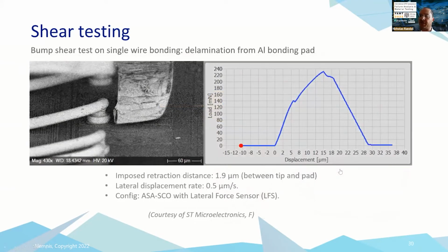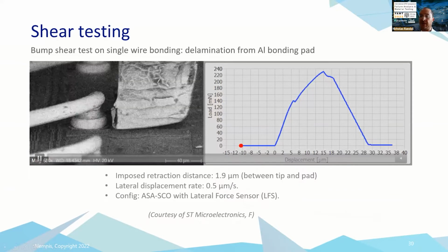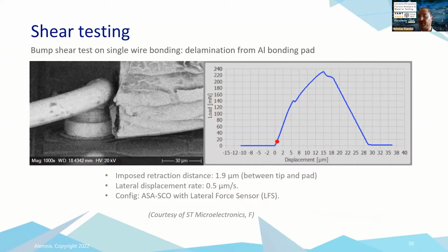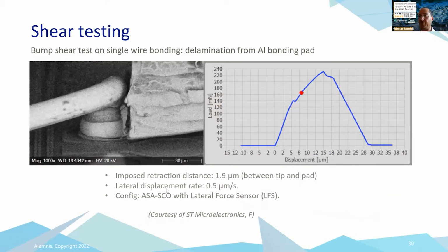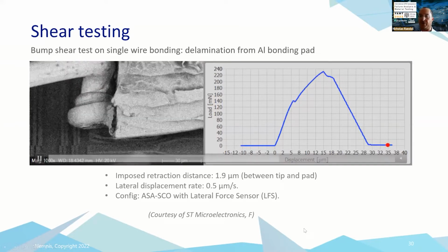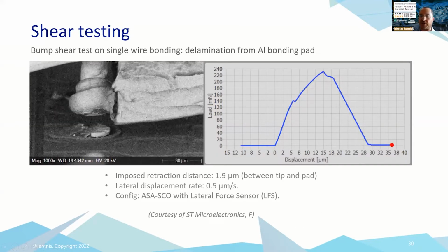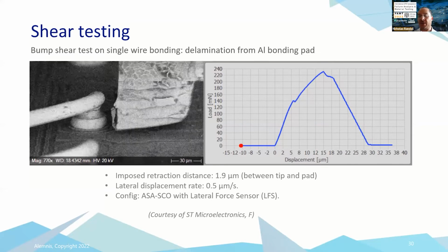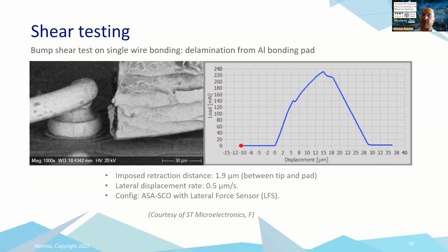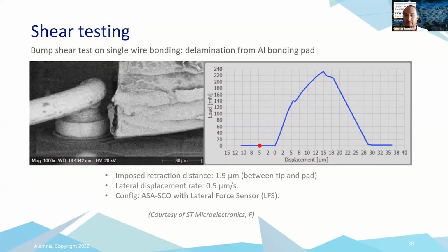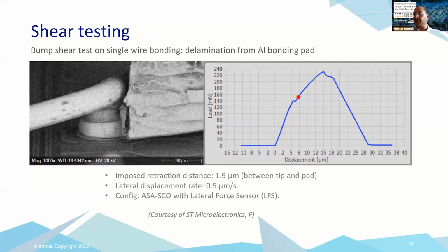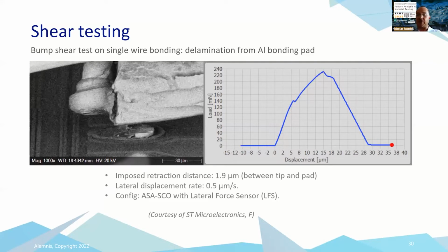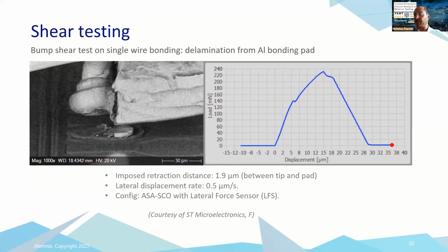This is a bump shear test. So we're using the lateral force measurement of the system to rip off a single wire bond, and we do that using a special truncated indenter. It's very nice to see this in real time because we can see how the bond is failing and where exactly at the interface. And we can also couple that with electrical testing at the same time.